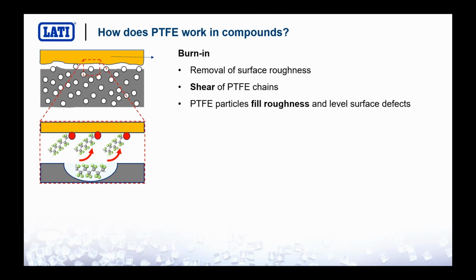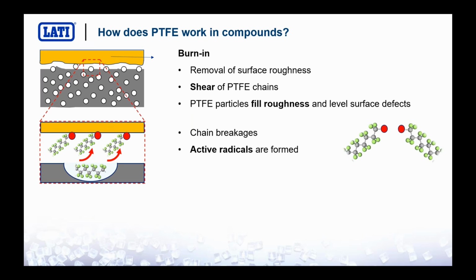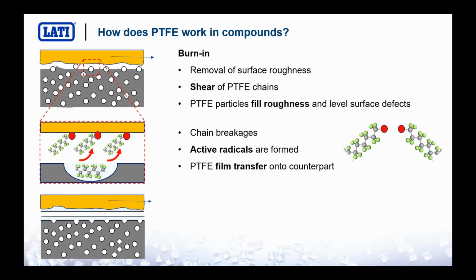The second step is the breakage of these very long PTFE molecules into several smaller molecules, smaller chains. So the chain breakage leads to the formation of very, very reactive molecules, very reactive radicals. These radicals are then transferred onto the counterpart. So there is a film transfer to the counterpart. So at the end, we will have PTFE on one, but also on the other surface of both materials. So we have PTFE sliding against PTFE,